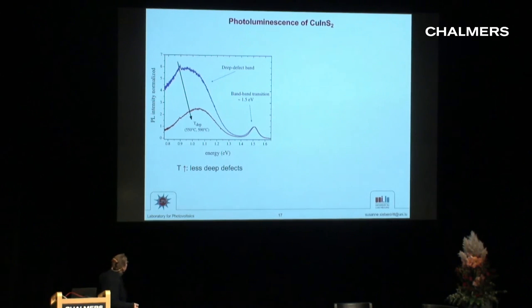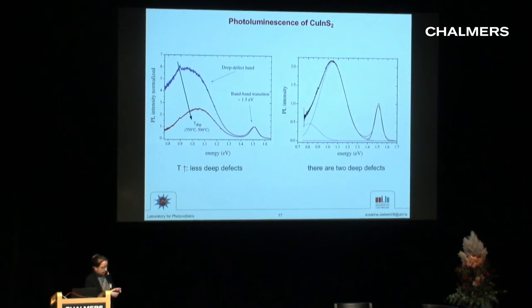And when we now do this for the sulfide with a low temperature process and a higher temperature process, you see this is the band-band transition, and this is a defect-related transition. So what we see is we have less deep defects when we go to higher temperature. And when we look closely, we actually see these are two. There's one and there's another one here. And a deep defect is bad for the solar cell.